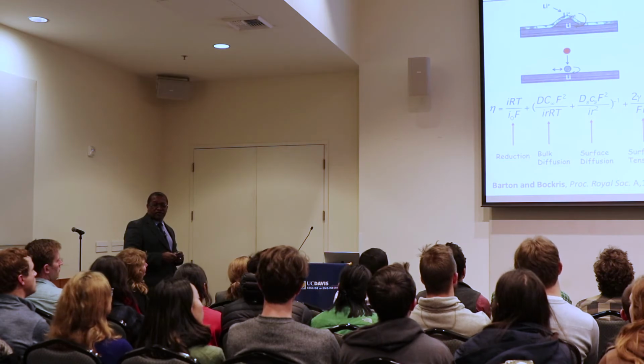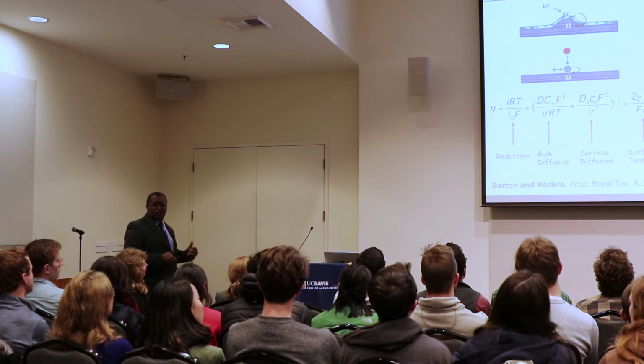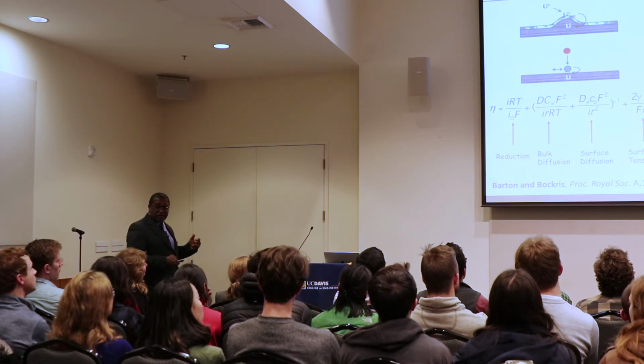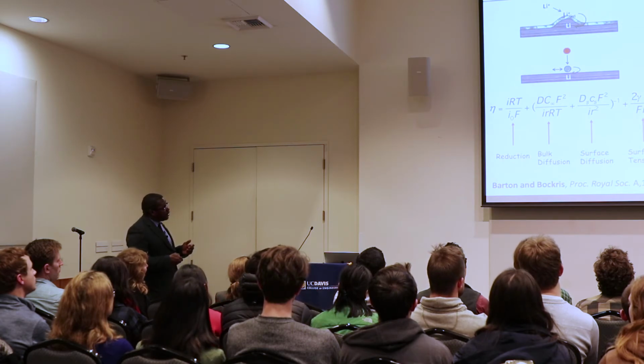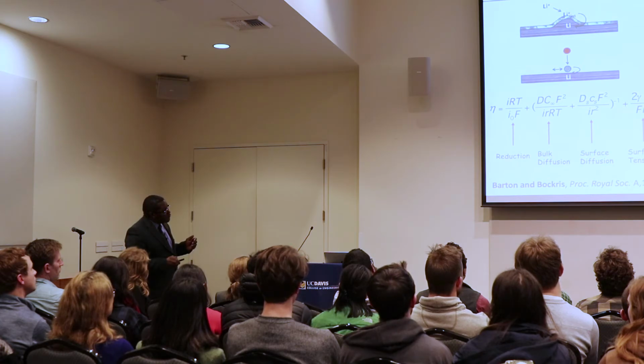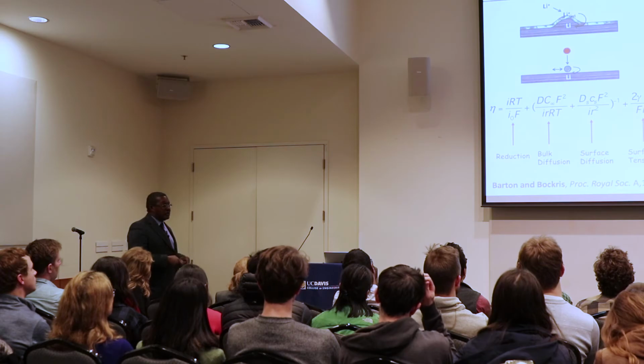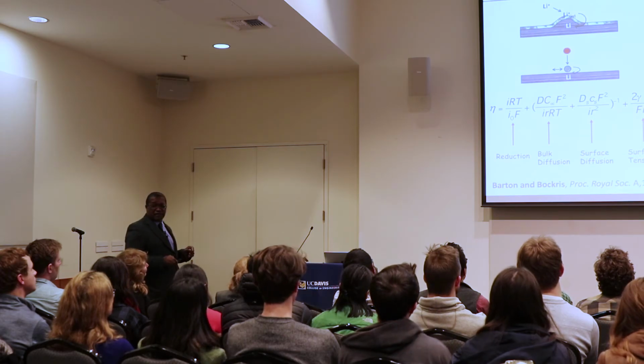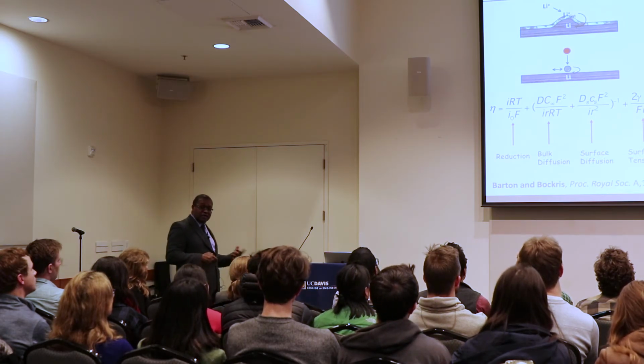You can also get out things like the transport properties in the bulk. We amended this model to include the surface diffusion, and by fitting this model to data, we can get information about lots of things occurring at the interface.